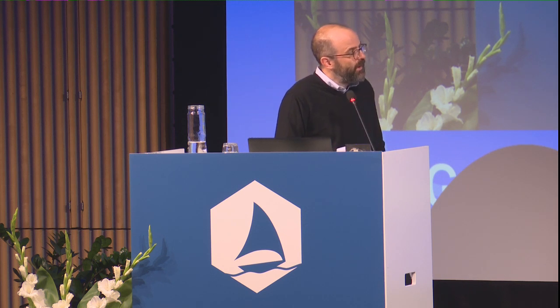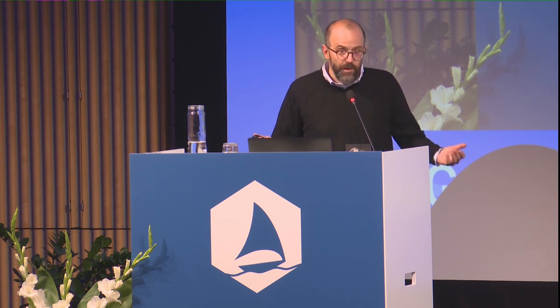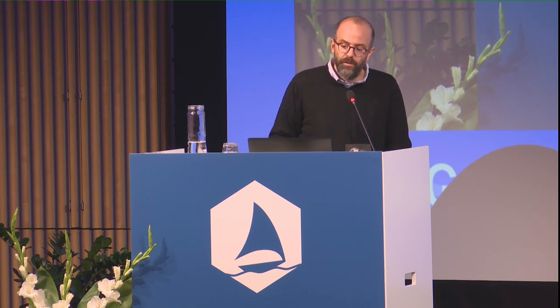And this flat band is interesting because its width is sufficiently narrow that you would expect that in this band, Coulomb interactions would dominate over the kinetic energy term. And in this paper, they theorized, and work that followed sort of theorized, if you could realize such a system, then this is a recipe for emergent behavior. So because Coulomb interactions dominate, anything could happen, from maybe getting magnetic ordering to getting superconductivity, et cetera.